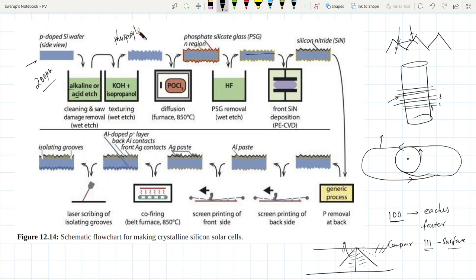Phosphoryl chloride, POCl3. This phosphoryl chloride we use in a high temperature furnace, at 850 degrees centigrade, and if you pass this phosphoryl chloride as a vapor, it diffuses into all the bare surface, and the phosphorus present in this composition will diffuse inside.